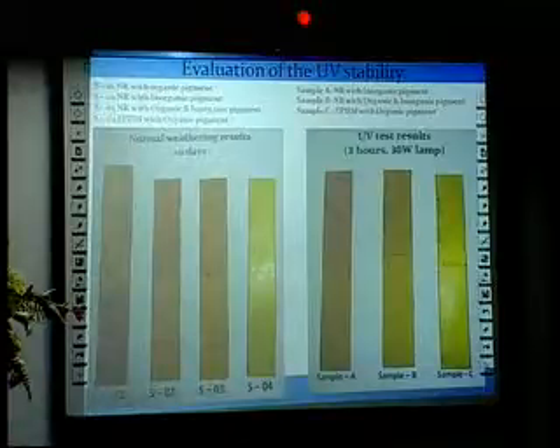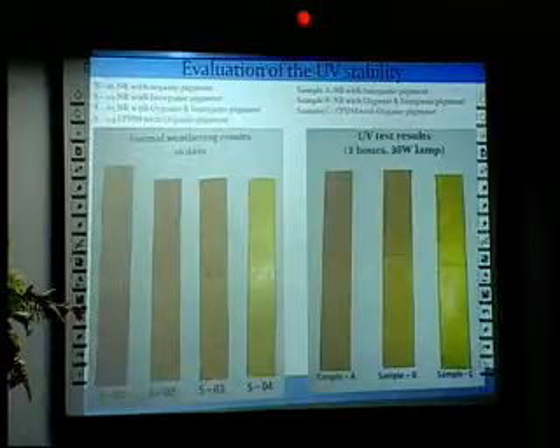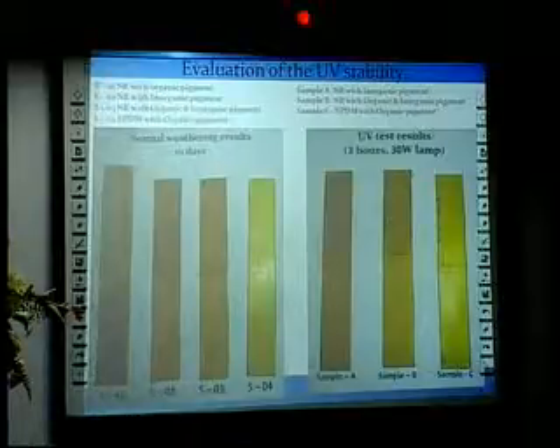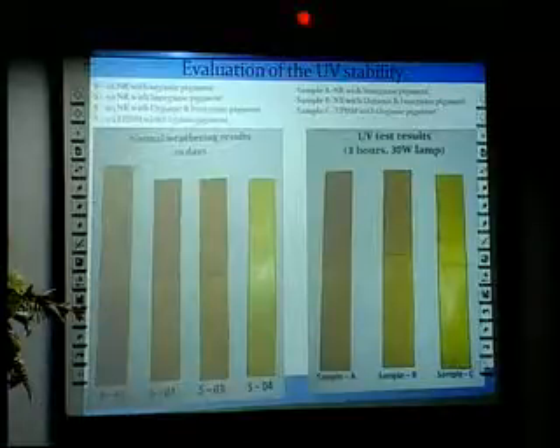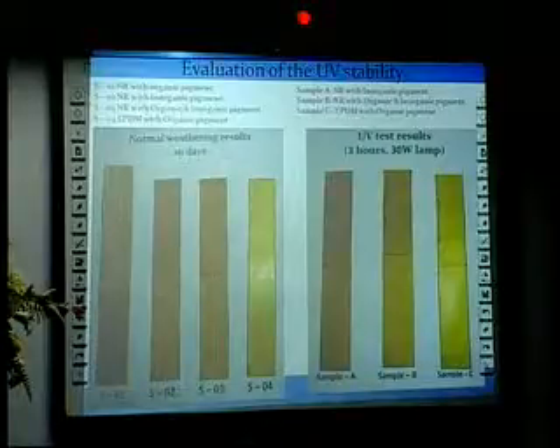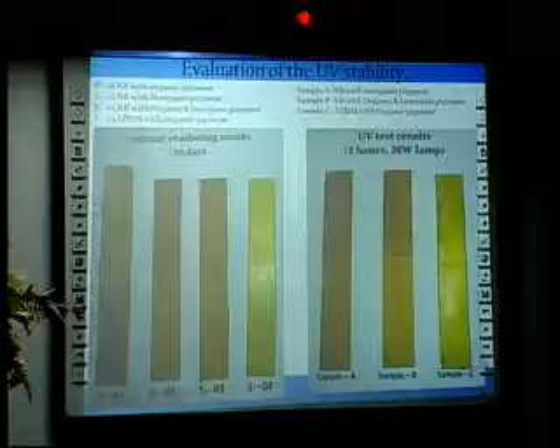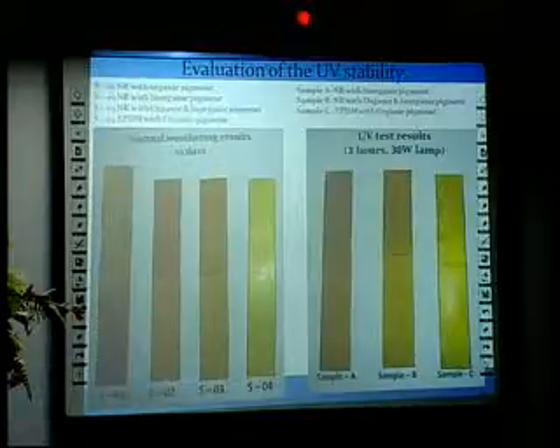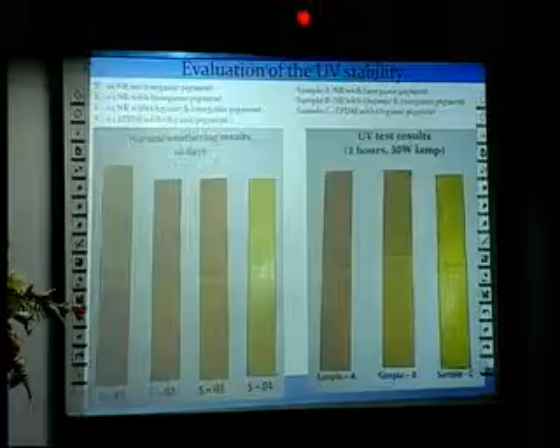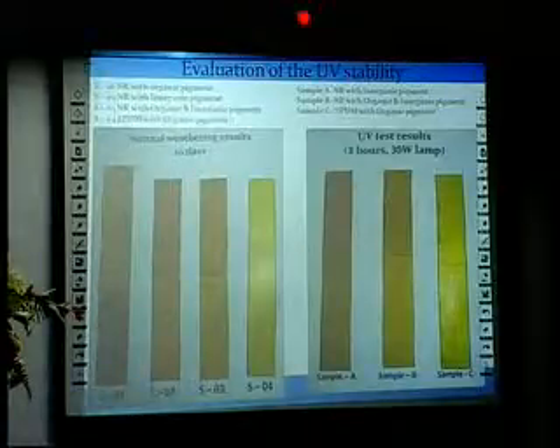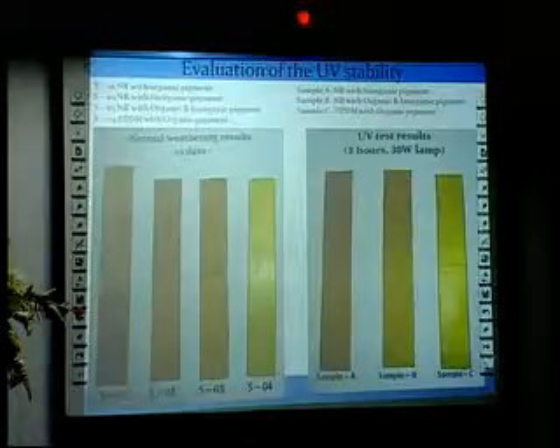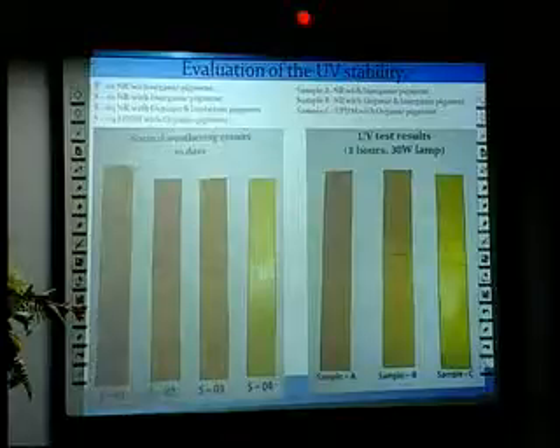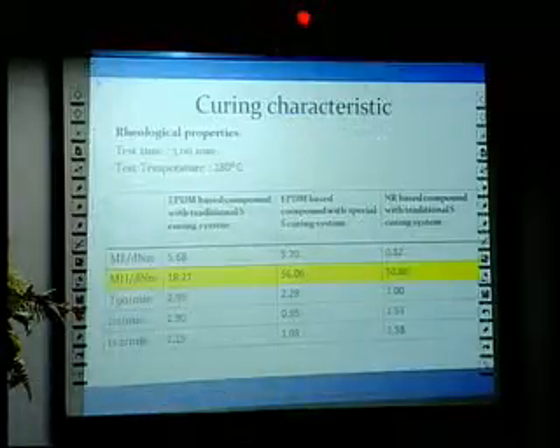Here, the discoloration appears mainly in the natural rubber-based compounds with all the pigments, inorganic, organic, and the combination of both. I already mentioned that the inorganic pigment has more UV stability than the organic one, but it did not enhance the UV stability in the natural rubber-based compound. In the EPDM-based compound with organic pigment, no significant discoloration appeared.